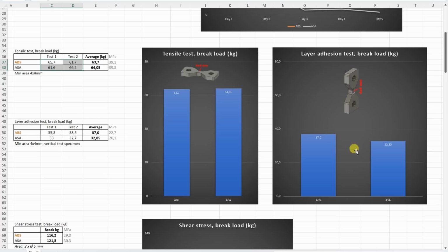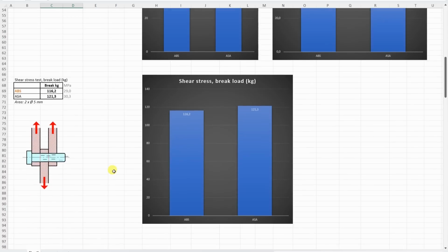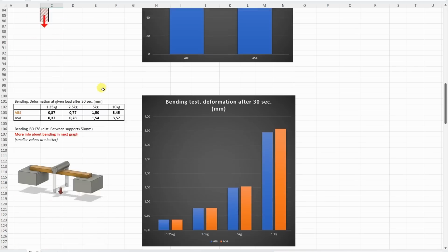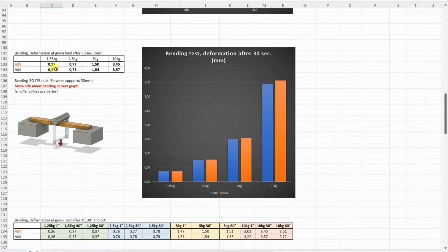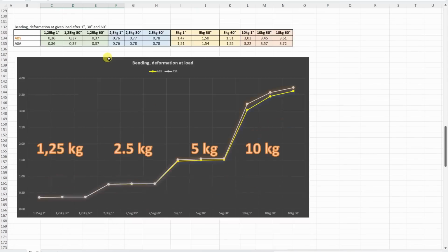On the layer adhesion test, this is very good. I mean, everything above 20 kilograms is very good for the ABS. On shear stress, again a little bit weaker compared to the other materials, but very similar between each others. On the 3-point bending test, this is the deformation after 30 seconds under these values. But this is more interesting.